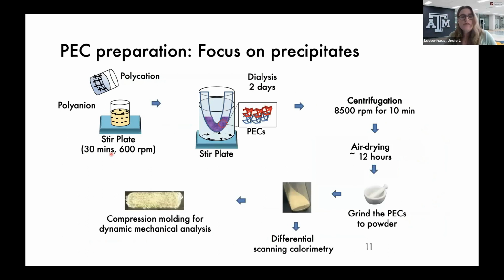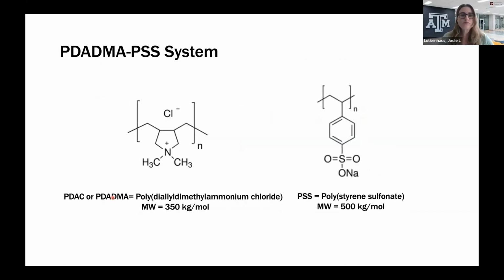To give you an experimental point of view, this is how we prepare and characterize the complexes. We'll mix the two polyelectrolytes together, and then we'll do some dialysis. This helps equilibrate them and eliminate some of that path-dependent behavior that happened in the mixing process. Any unassociated polyelectrolyte will diffuse out of the dialysis bag, and so we can really isolate the complex. Then we can further isolate it with centrifuging. We air dry it, and then we can obtain a powder. With the powder, we can do DSC to get the glass transition. We could also process the powder and do some compression molding for dynamic mechanical analysis.